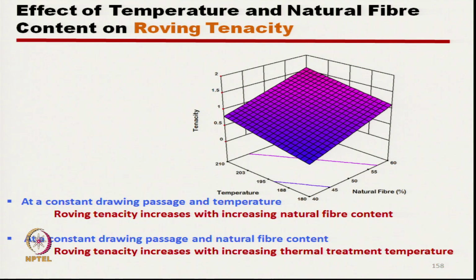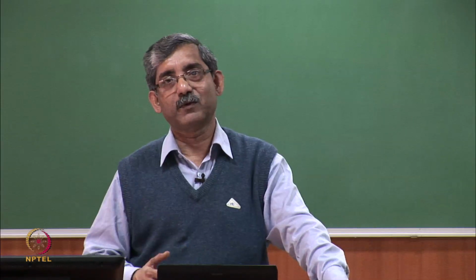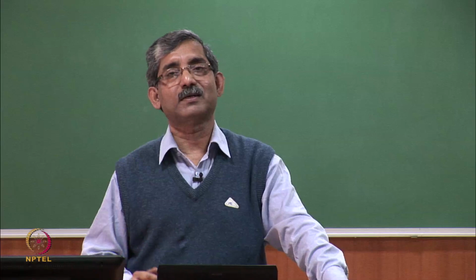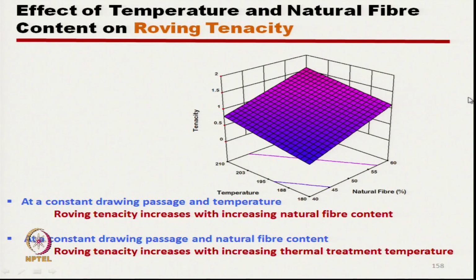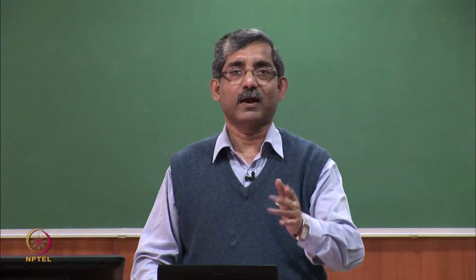So, if we increase the reinforcing component up to say 60%, from 40 to 60 it is continuously increasing, but this trend may not be the same if we further increase to 70-80%, because the matrix component has to be there, because the fibers are in parallel stage.